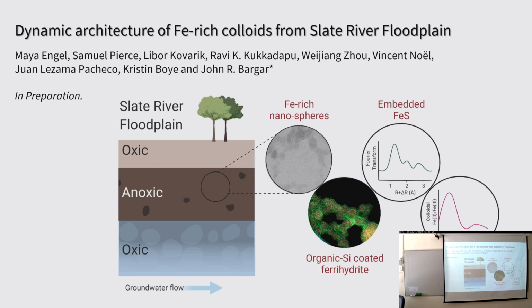I think that the most important finding of this study is that we have detected natural oxidized iron-rich colloids that are abundant in anoxic-reducing conditions. We've also seen that the composition is highly dynamic and seems to be very much dependent on the season. So we're working on summarizing this now into a manuscript that's going to be focused on the characterization of these colloids. We're also working on linking the colloid dynamics to our results on hydrology and pore water chemistry at the field site. So anyone who's interested, stay tuned.